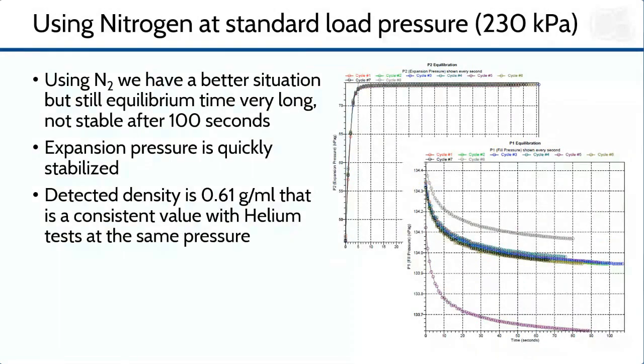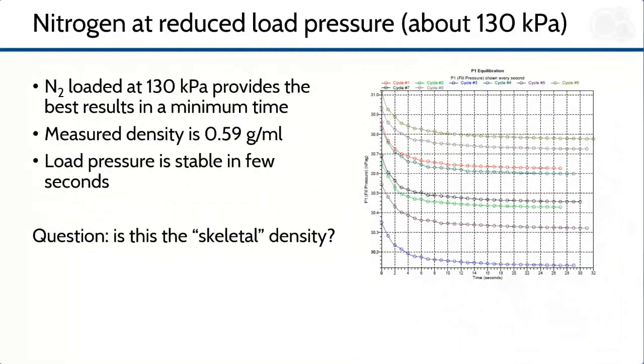Sometimes it is useful to use nitrogen as measuring gas rather than helium when a diffusion limitation is present. Nitrogen is a larger molecule than helium and might not diffuse in smaller pores or cavities, making the analysis time reasonable. In case of this instant coffee, the situation improved a bit using nitrogen at 230 kPa, but still diffusion is present and equilibration requires more than 100 seconds for every cycle. Finally, we tried to use nitrogen at a reduced loading pressure of 130 kPa, finding the best procedure to shorten the equilibrium time.